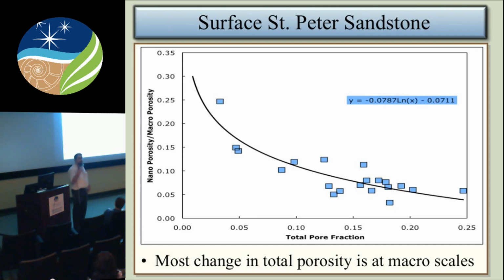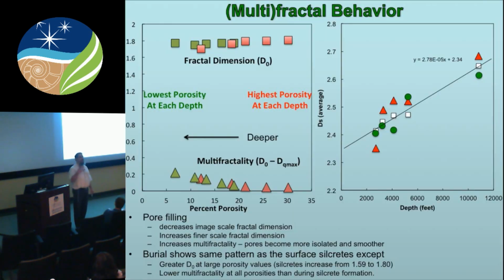Now remember I mentioned earlier that we can also measure from the slopes of the scattering curves what the fractal dimensions are for these materials. We can get that as well from the images. We can calculate the fractal dimensions and what are called the multifractal dimensions, which is how fractal dimension scales as a function of size. And we've seen the same result for both types of sandstones that we've looked at.